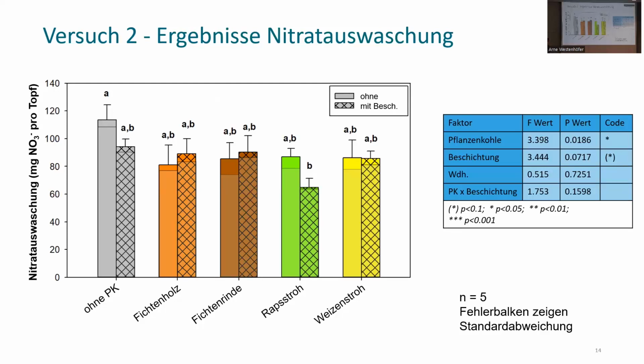Here, the results, the nitrate leaching. The lower part of the bar, which is brighter, that's the result of nitrate leaching of the first heavy rain event. And the little bit that's on top of it is the second heavy rain. So it's not that much if you compare it to the other bar. And so the biggest chunk of the nitrate that was there in the soluble form was washed out right away.